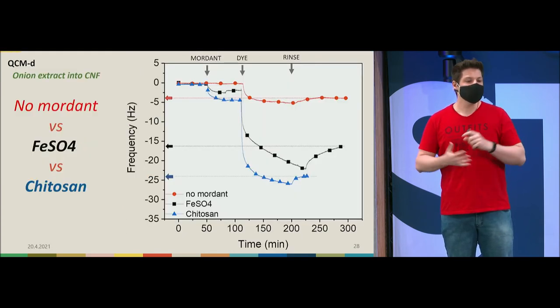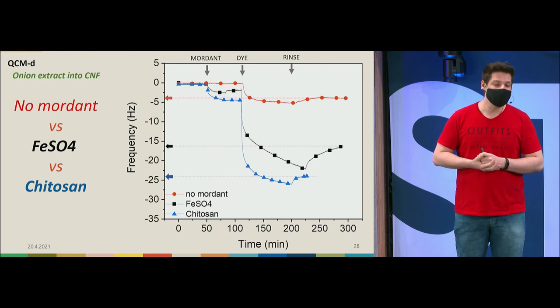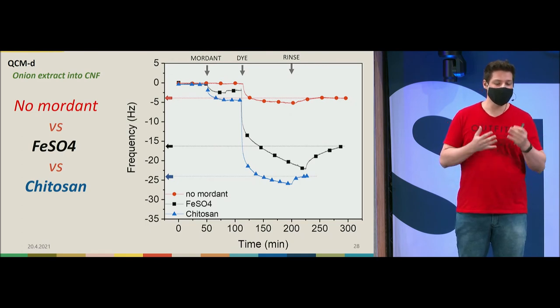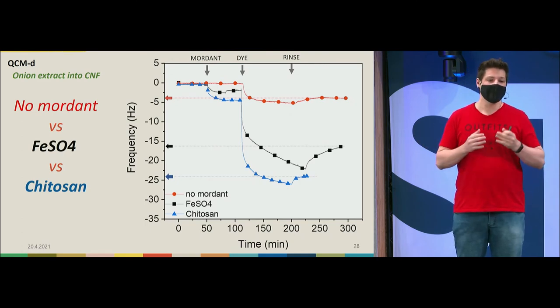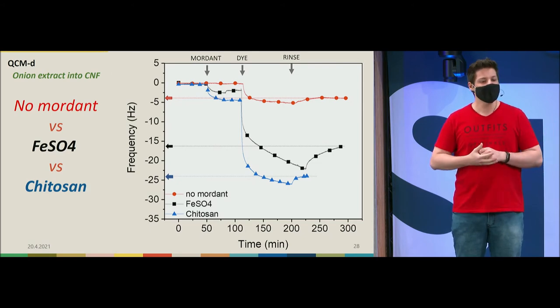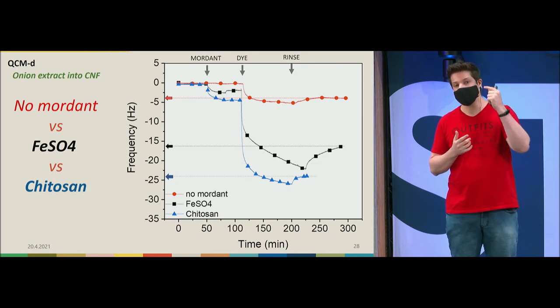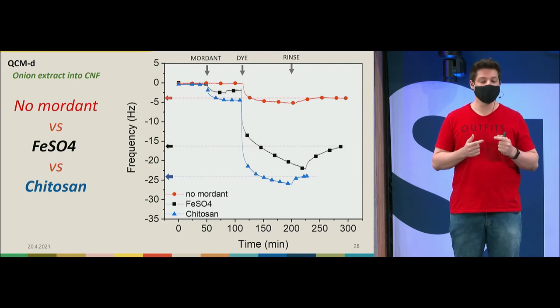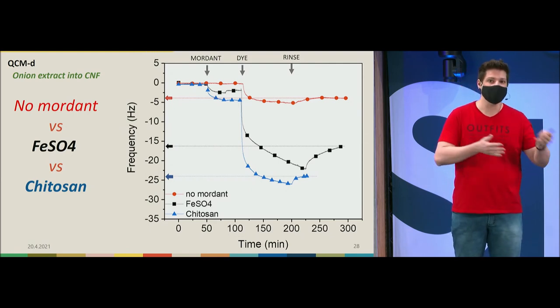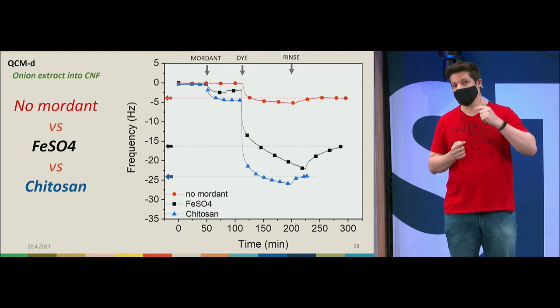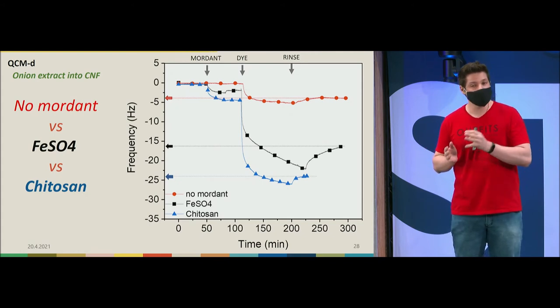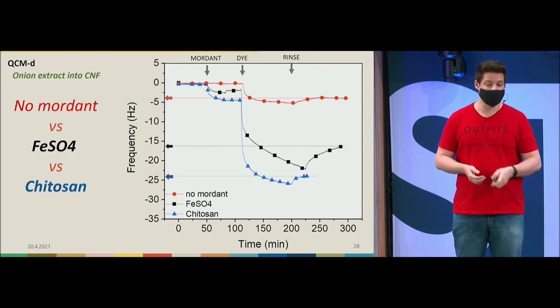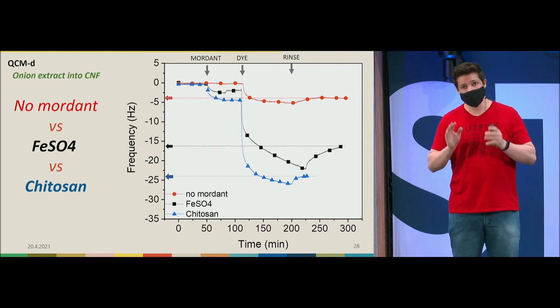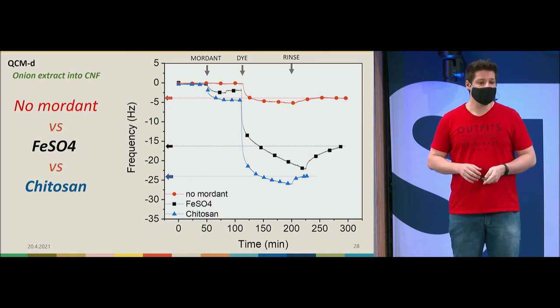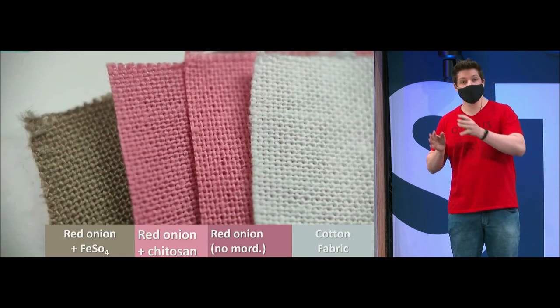And our initial results were very exciting because, as you can see, the red curve I have already shown is the material without any mordant. When we add the metal ion, of course, the absorption was improved because this is how they do it in industry. But by using chitosan, in terms of absorption, it worked even better. We had even higher absorption. And not only that, Monika already mentioned this, but chitosan also helped to keep the color.